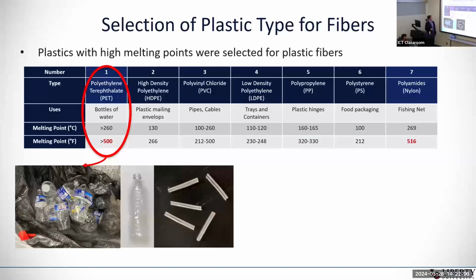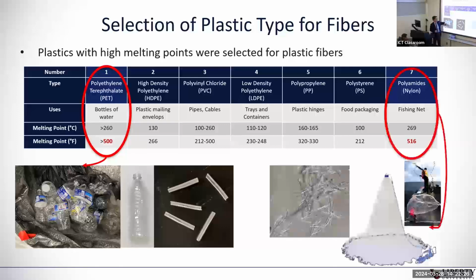The very first thing was the selection of the types of plastic for fibers, based on the melting point. We took this PET plastic and fabricated it to a size of 20 by 5 by 20 millimeters, and then we also picked this nylon, which is from fishing net. When you chop it, it looks a little different from the PET waste plastic, but we don't need to cut by width. So we just cut the fishing net into 17 millimeter lengths. And then we used these two different types of fibers in the asphalt mixture.